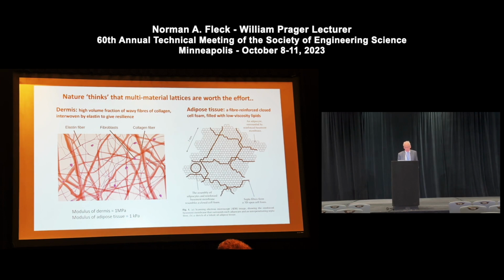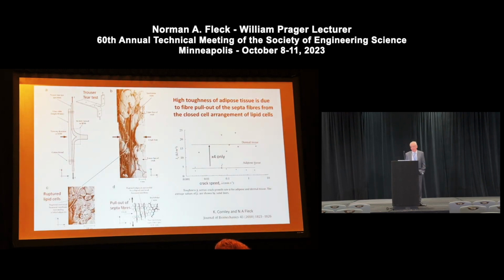If you look at the stress strain behavior of skin, of the dermis, and compare it with adipose tissue, with fat, they're different by a factor of 1,000. So the modulus of the dermis is a megapascal, that of rubber, that of adipose tissue is a kilopascal, a factor of 1,000 less. You don't need much stiffness for fat cells. We looked at injection of needles and also liquid jets into human skin and pig skin too,